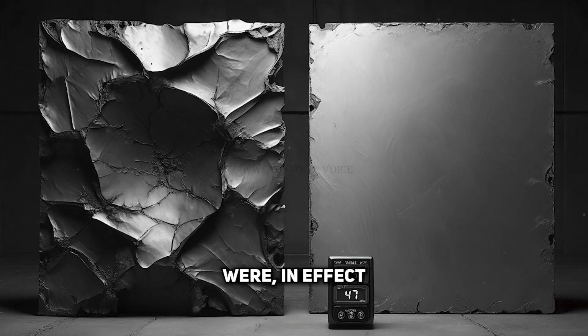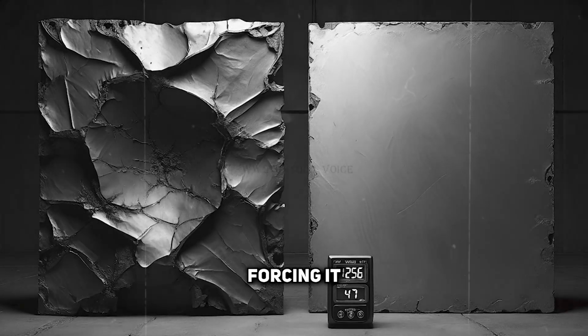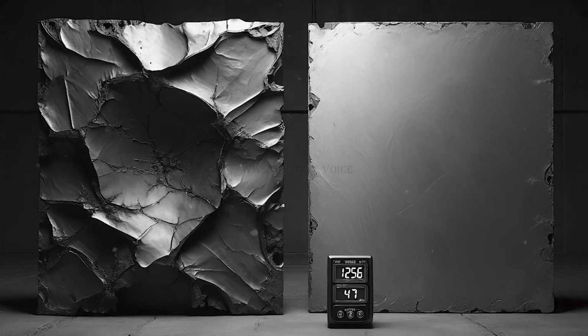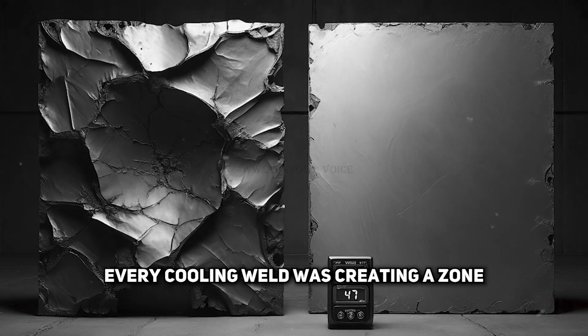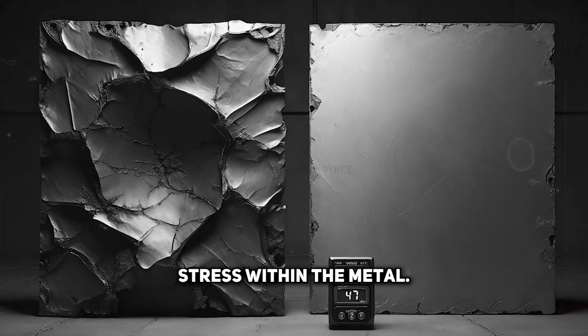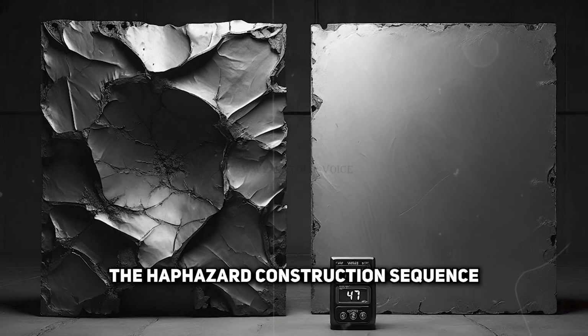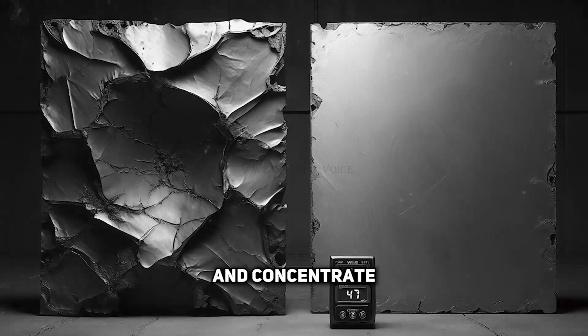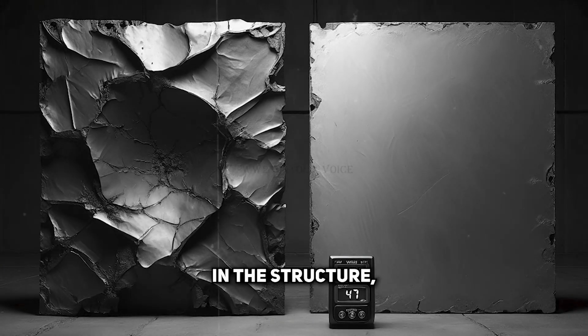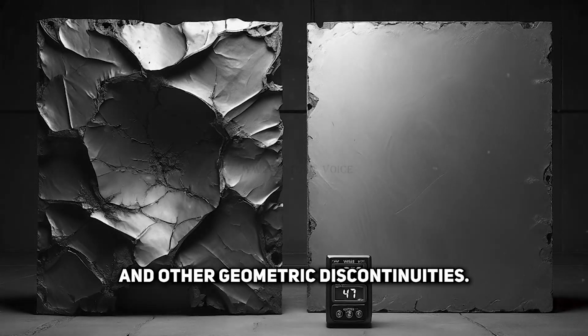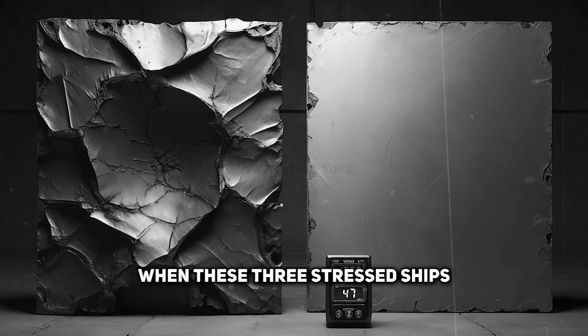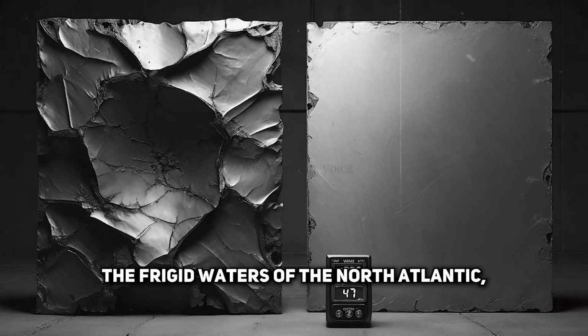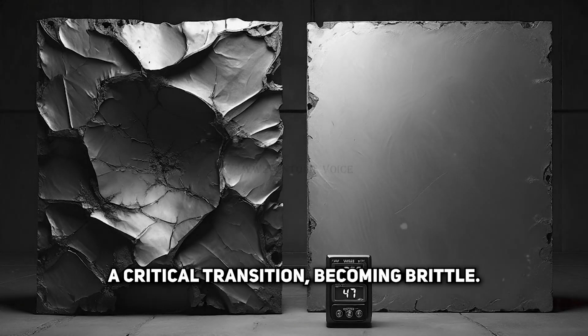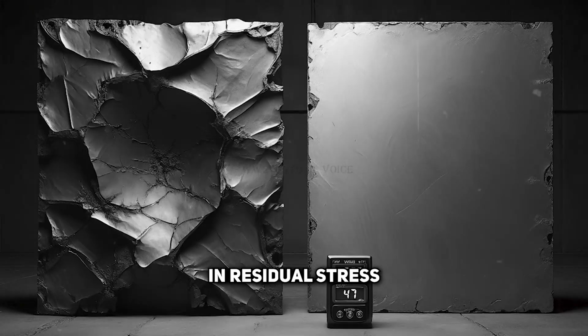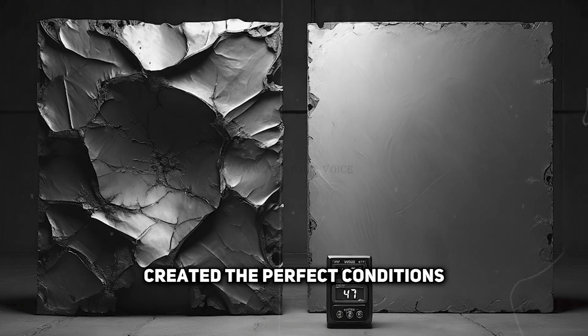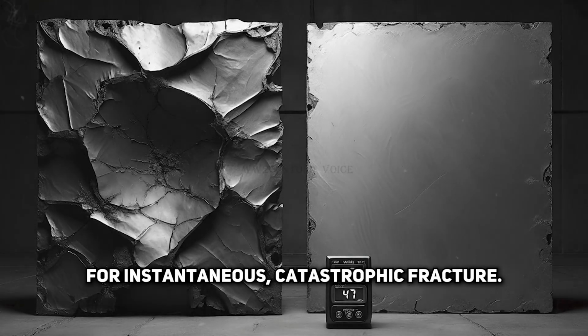The established welding procedures were, in effect, systematically torturing the steel, forcing it to accept and retain destructive stresses that it would carry for its entire operational life. Every cooling weld was creating a zone of residual tensile stress within the metal. The haphazard construction sequence meant these individual stress zones could accumulate and concentrate at specific, vulnerable points in the structure, particularly the sharp corners of hatch openings and other geometric discontinuities. When these pre-stressed ships subsequently encountered the frigid waters of the North Atlantic, the steel underwent a critical transition, becoming brittle. The combination of locked-in residual stress and this newfound material brittleness created the perfect conditions for instantaneous, catastrophic fracture.